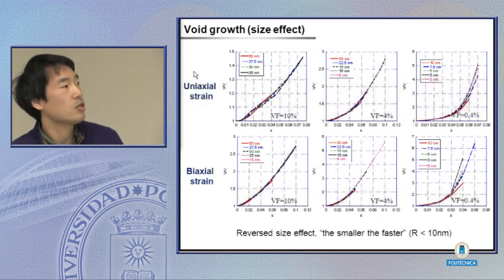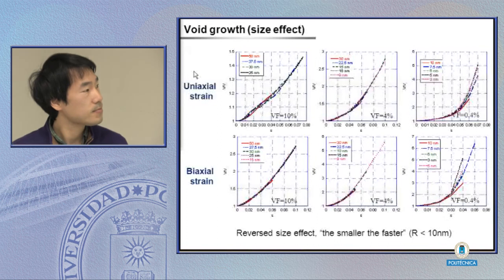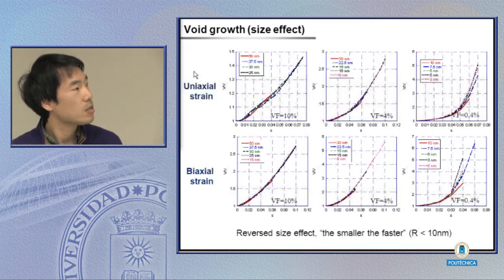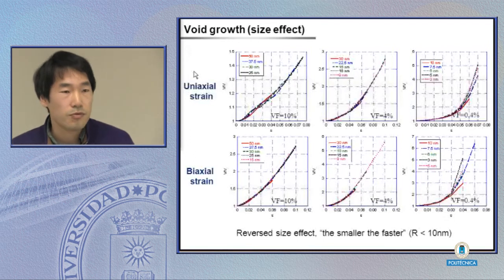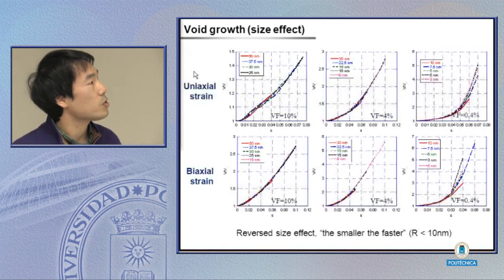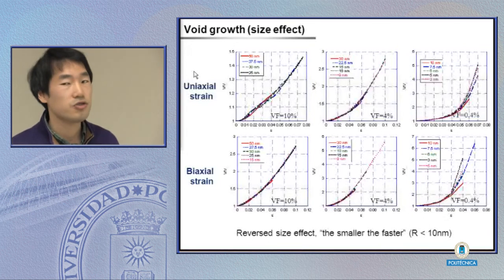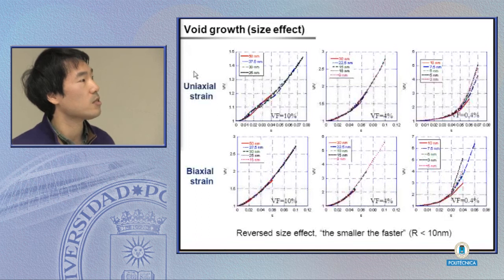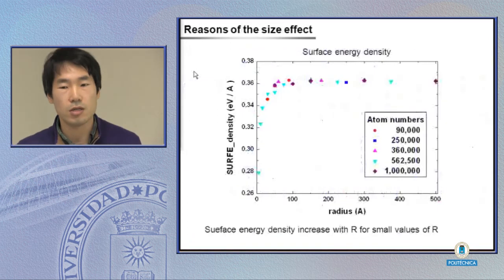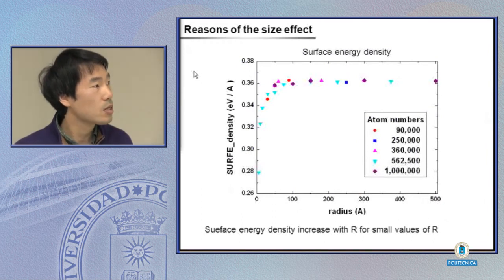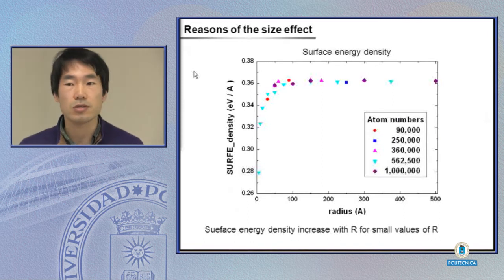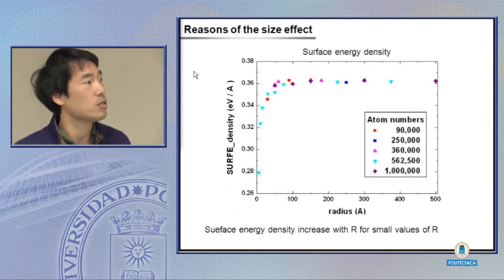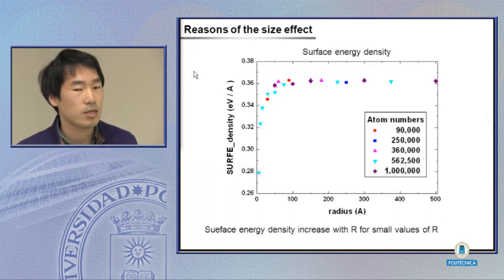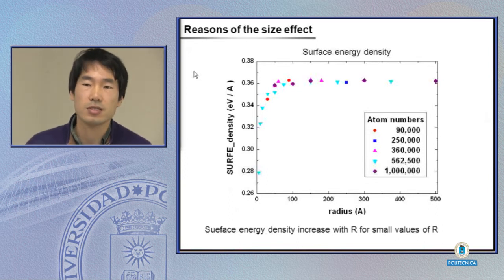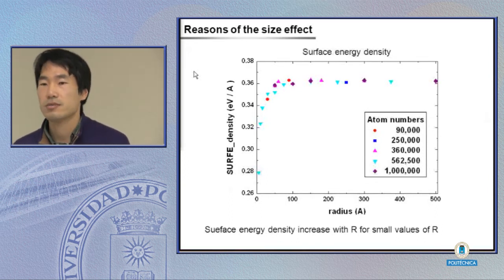And the voids are crossed by the dislocations and the stress field. And we take the void growth. And as you can see, usually the molecular dynamics gives no size effect, except for a very few size cases of the void. When the void radius is less than 10 nanometers, it gives a size effect, but it's a reversed one. The smallest void means the faster void growth. It means that there is much less hardening.